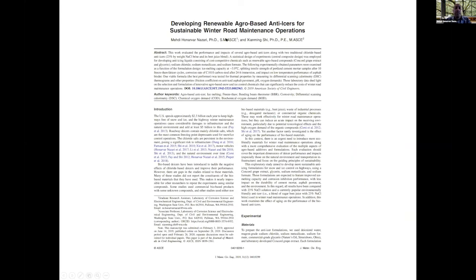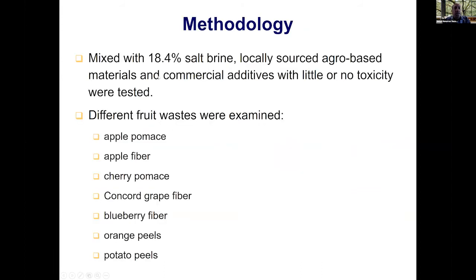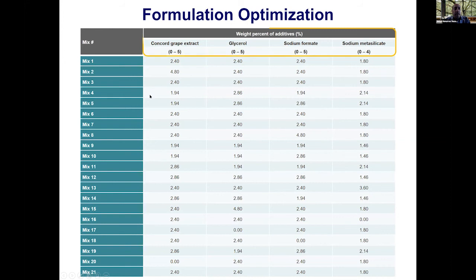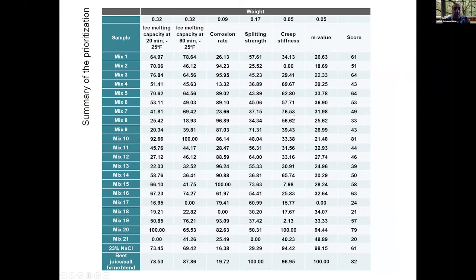In the next step, we use different fruit waste to see which one works best for the green deicers, and we published this research in 2019. This time we use less salt, 18.4, and among the different fruits that we tried, the Concord grape had the best results. So this time we used central composite design and glycerin, sodium formate, sodium metasilicate, to produce green deicers.